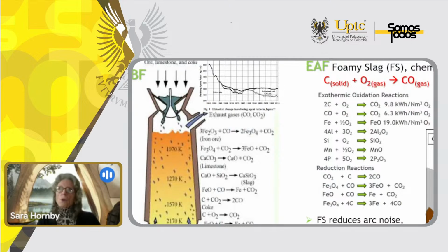Carbon dependence is both with the blast furnace and the EAF, and I'm not going through all of these calculations, but you can see on the left-hand side that CO or CO2 is prevalent throughout the blast furnace, especially because they use coke to support the burden in the blast furnace. That is why we have the 2.2 tons of CO2 per ton of steel.